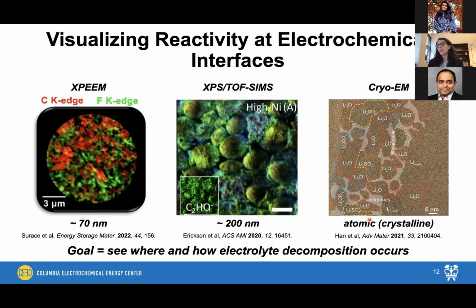And then, of course, we can borrow techniques from structural biology, so things like cryogenic electron microscopy, to start to assign the different chemical components that are present in our CEI on the surface of our cathode. And here, if we have a component that is crystalline, because we're actually looking at the individual lattice planes from these different components, we can get atomic scale resolution. But of course, the catch is that the species we're looking at has to be crystalline in order to definitively assign the chemical composition here.